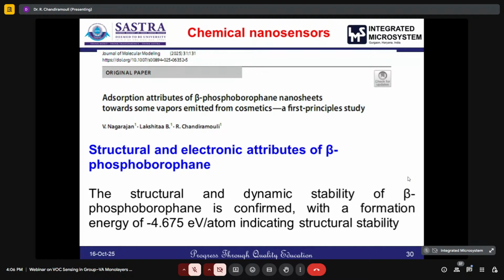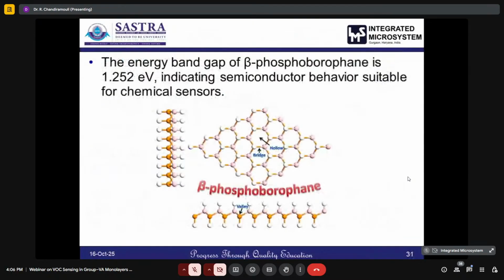First, we explore the structural and the electronic properties of beta phosphoborophane. First of all, we have to ensure the structural and the dynamic stability of beta phosphoborophane. That is confirmed with the formation energy for the static structural stability. By the value of the formation energy of minus 4.67 electron volt per atom, the static structural stability is ensured. The next thing is we have to calculate the energy band gap. That is very important. The energy band gap of beta phosphoborophane is 1.252 electron volt, which means that it is a semiconductor, so it can be suitable for the chemical nanosensor.